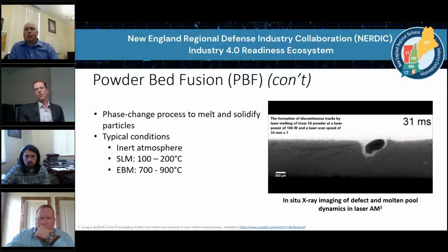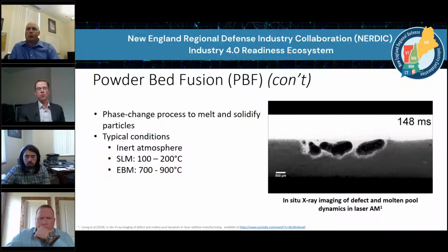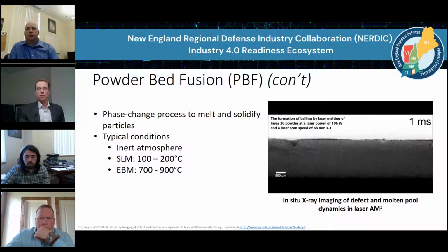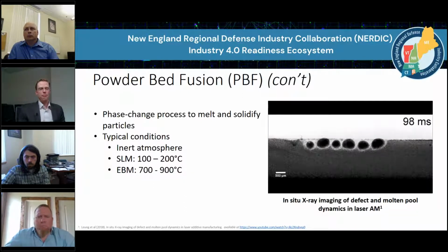The other thing you need to consider with powder bed fusion is that you typically need an inert environment. Powder has a high surface to volume ratio, and it can be reactive in nature and lead to explosions. Typically, you do powder bed fusion in some sort of inert environment within the machine itself.